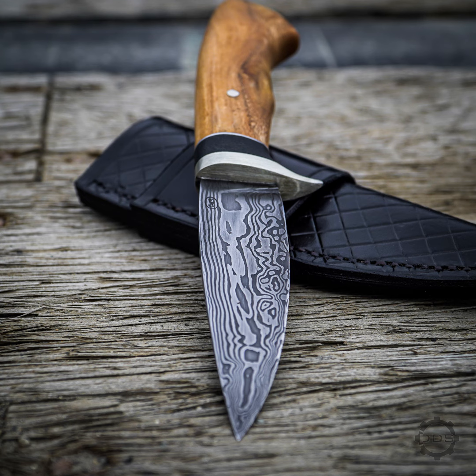So you're like, what are you going to use it for? I'm going to process my moose with it. You're like, oh, like cut ribs and stuff off. And okay, man, I'm confident in my heat treat, I think, but that's a lot of abuse. Yeah. So I forged it down to about 3/16 thick at the edge, and then I ground it like an axe from there. Half of the blade was hardened, and the back half of the blade was soft to springy. So there was a lot of room for shock absorption.